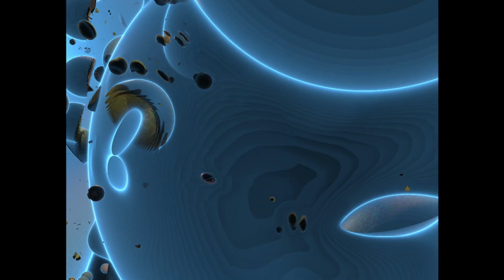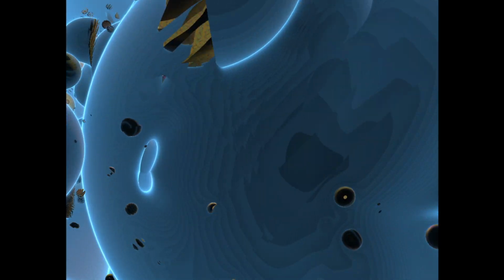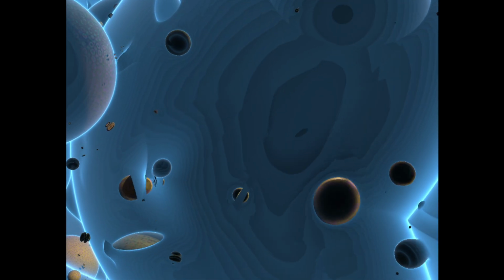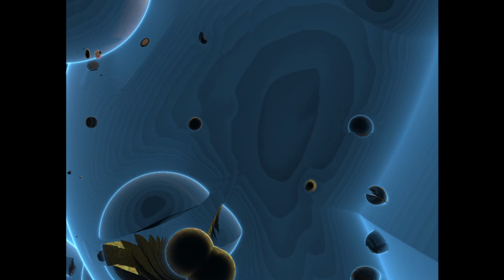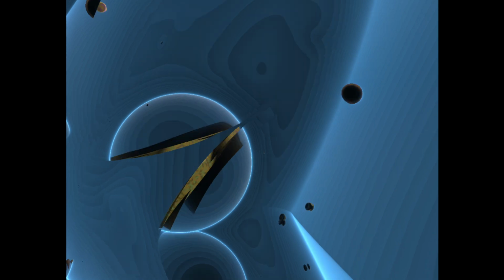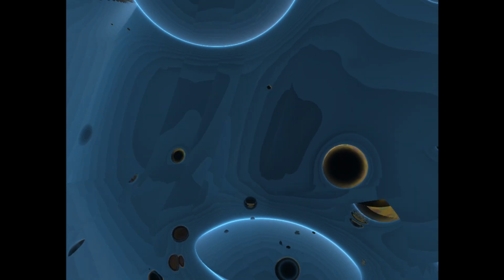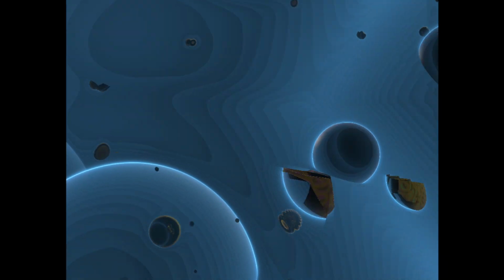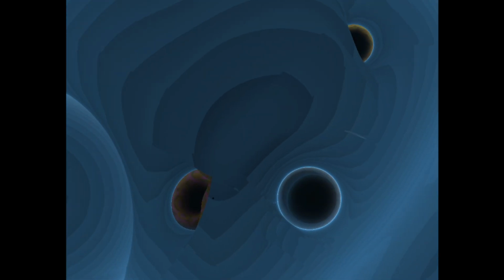Chemical substitution is a huge one. We mentioned carrier doping, swapping atoms to add or remove electrons. K for Ba adds holes, Co for Fe adds electrons. And that directly shifts the Fermi level, changes the pocket sizes, messes up the nesting, suppresses the SDW, and often reveals the superconducting dome. Standard procedure.